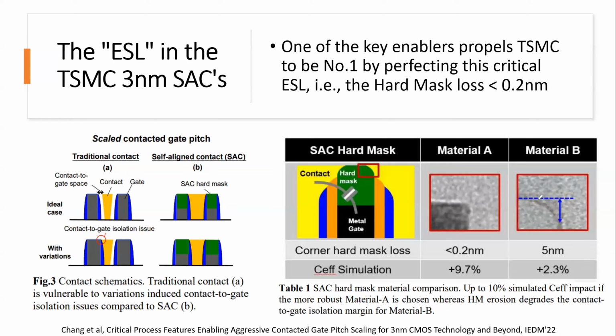And here is still vertical, meaning that the etch did not hurt it. Their selectivity is very high here. See, the mask loss after etch is less than 0.2 nanometer. That's how good they can control, meaning that the etch chemistry did not hurt it at all. Just to give you a perspective, this is 2 angstrom. An atom is about 3 angstrom. And this is less than 1 atom. So it's nothing lost here.